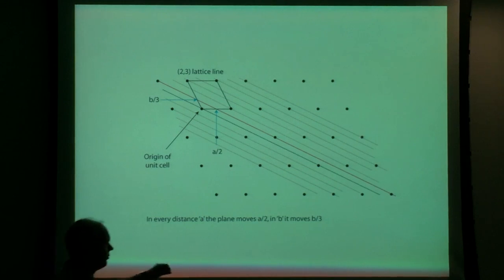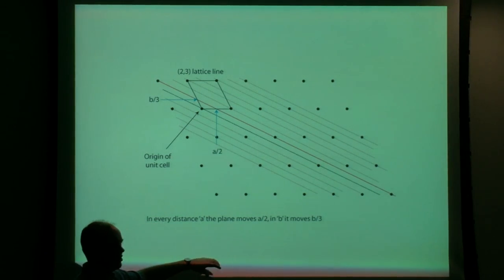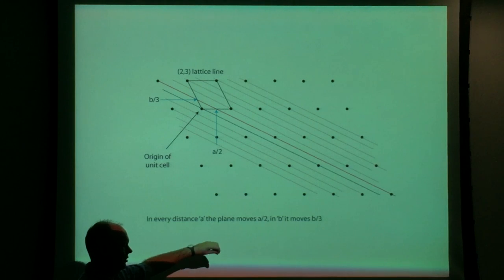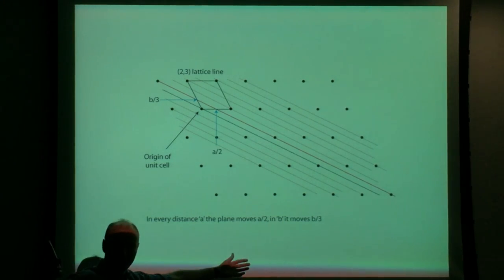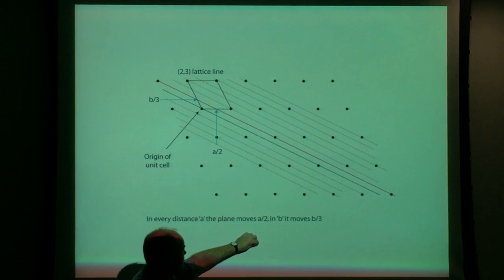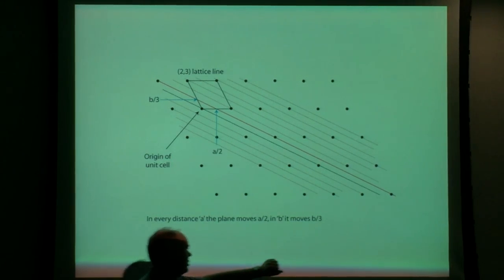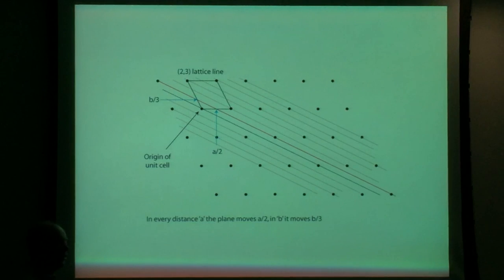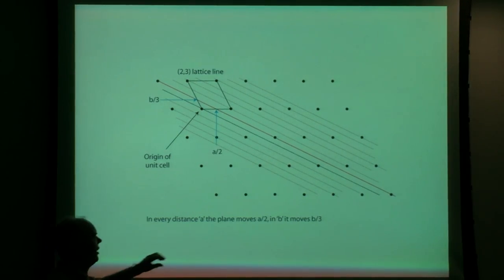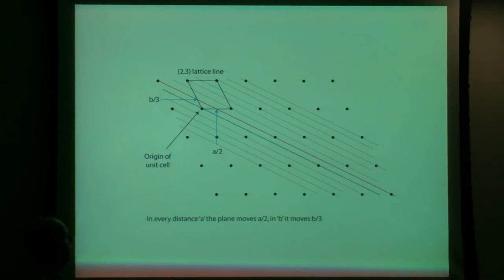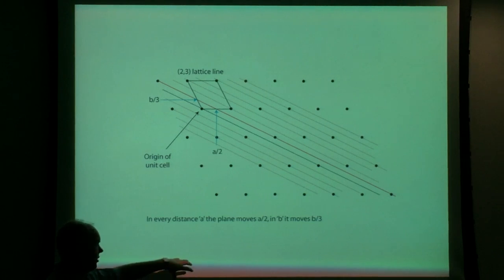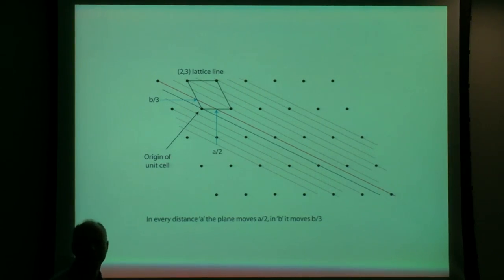As you're sampling finer through space and the Miller indice is higher, the d-spacing that you're looking at is a smaller spacing. Your angular extent of the spot increases. So instead of spots being around the beamstop at the center of the pattern, we're seeing spots that are further away from the beamstop. And those spots are less intense because they're actually sampling less of the reciprocal lattice points. There's a lot more math to that as well. There's a lot of other things involved. But that is conceptually a very simple way to think of what the Miller indices mean and also why a diffraction pattern is intense at the center, and then gets less intense as it goes further out.